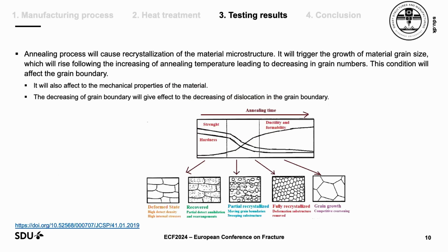And unfortunately, because of some technical problems, we couldn't use our XRD device. We planned to use it and present what is happening at the grain scale and the microstructure, but we couldn't because of some technical problems. I hope probably in September we can use it to better connect the microstructure, like the formation of the grains and so on, to what we saw from the macromechanical testing. So the literature, for example, says recrystallization, grain growth, and so on, and the reduction in the dislocation density. What we wanted to see is whether that is the case in our samples, and mainly to obtain the optimum temperature for the heat treatment. We tested different temperatures, but not all of them can be useful, specifically when it comes to dynamic testing. We did only static testing, but we wanted to extend this to dynamic testing. So we couldn't do any XRD, and the explanation just comes from the literature.